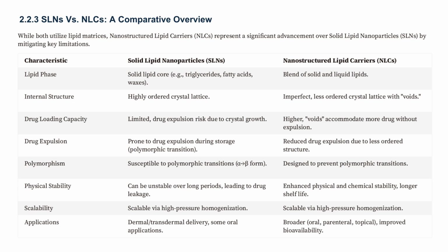This table provides a head-to-head comparison of first-generation SLNs and second-generation NLCs. While both are easily scalable using high-pressure homogenization, NLCs clearly take the lead in performance. By blending solid and liquid lipids, NLCs solve the major physical stability issues of SLNs, specifically preventing drug expulsion and polymorphic transitions over time. This upgraded structure ultimately gives NLCs a much longer shelf life and makes them suitable for a broader range of applications, including oral and injectable delivery.